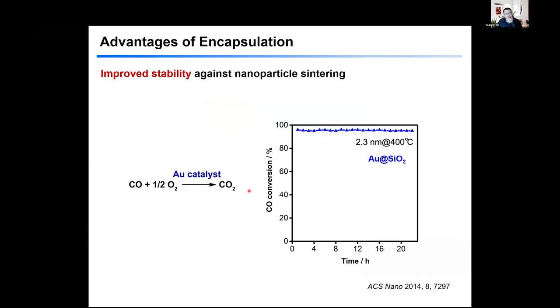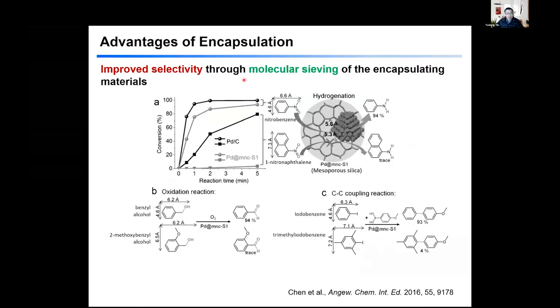Okay, so last, I just want to use 1 minute to talk about the advantages of encapsulation. Apparently, the first advantage is the stability. We can actually have very stable performance over a long time at high temperature. Second, this encapsulation brings additional materials that wrap the surface, so we can control the porosity on the surface, and we can screen the reactants based on their sizes. The smaller ones can go through, and you can have high reactivity. The larger ones cannot, and then you have really no reaction happening.